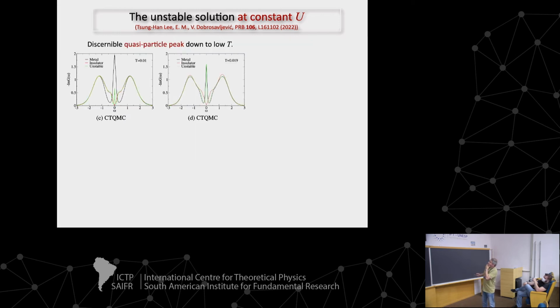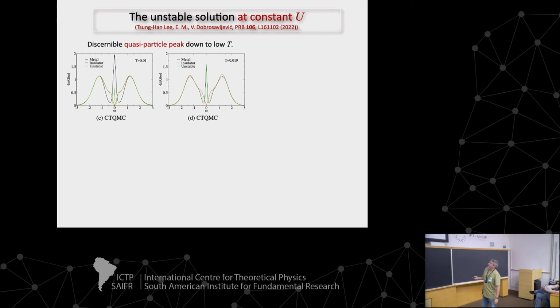Now the other thing you can do is you can plot the density of states at the domain wall center. This is for the three phases, the metal, the insulator and the unstable solution. The unstable solution is the green curve. What you see here is that even at low temperatures, you still see what we call a quasi-particle peak. In the metal, you have a very well-defined quasi-particle peak. These are the quasi-particles, the free carriers of the strongly correlated metal. But even in the unstable solution, you have a very small peak there. In the insulator, the peak is gone. You open up a Mott gap, and the peak is gone. But even in the unstable solution, at both temperatures here, you still see a small peak in the middle.